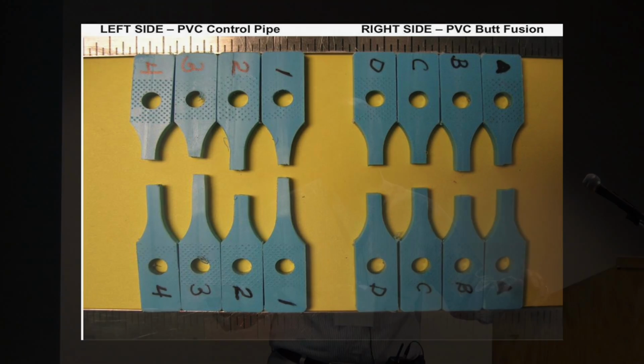What we then did was to compare these results to a published report where tensile testing was done, but in this case it was high-speed tensile impact. This is a newer test method that was developed by McElroy Manufacturing and has been used for polyethylene for a number of years. This testing was also done by another laboratory on PVC butt fusion joints.